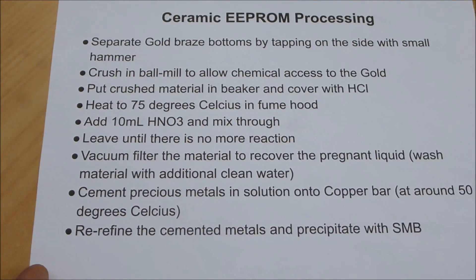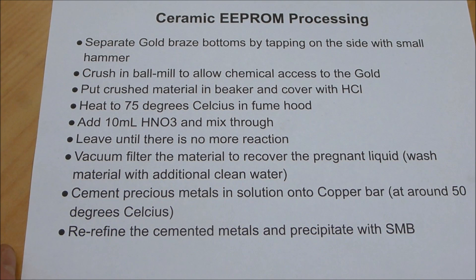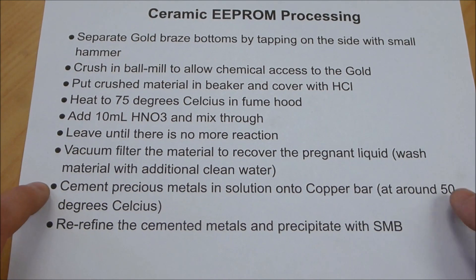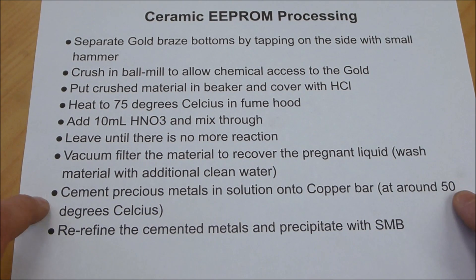So I end up with a beaker of this pregnant liquid. What I always tend to do next, instead of trying to precipitate the gold from that beaker, is cement any precious metals in the solution onto a copper bar. I usually heat it to around 50 degrees Celsius or so to do this.